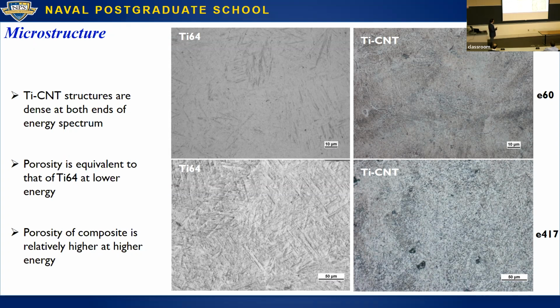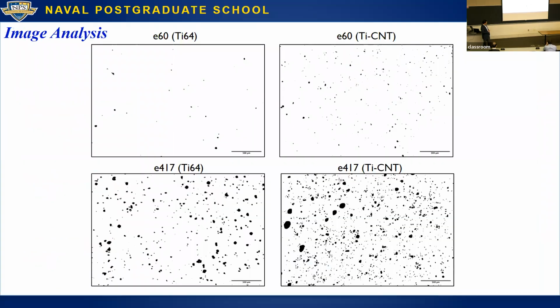But the biggest difference, if you just compare between Ti-64 and Ti-CNT, is you actually get much finer structures. And the structure of a Ti-64, if you're not familiar with it, it's mostly an alpha beta structure. So you've got these alpha needles that are HCP, and then you've got the beta phase that's BCC, and that's the more ductile phase. So it essentially has a good combination of ductility and strength. But the Ti-CNT structure under identical conditions, just the addition of 1 volume percent CNT, that's actually all we've gone to in what I'm presenting here, gives you a much finer array of needles.